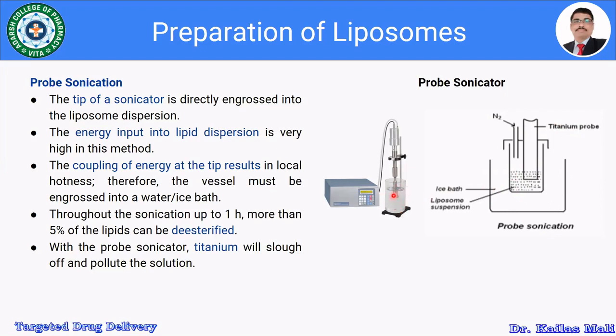The coupling energy at the tip of the probe sonicator results in local heat generation. Throughout sonication lasting up to one hour or more, more than 5% of lipids can be de-esterified — that is the main issue with probe sonication. Additionally, since the probe is made of titanium, titanium will slough off and contaminate the solution.